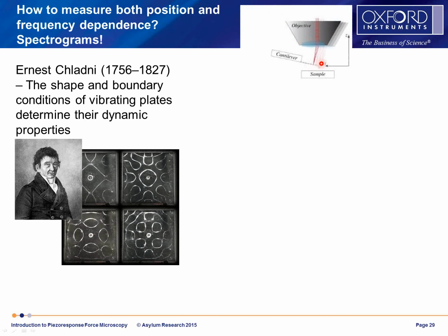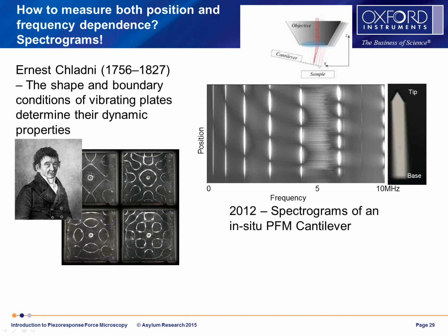We scan those photons using the optical detector and the AFM along the length of that cantilever. At the same time, we vary the frequency. We just sweep the frequency from, say, 0 to some high frequency. In the case I'm about to show you, 10 megahertz. And you generate these kind of pretty-looking maps of frequency and amplitude as a function of position from the base of the cantilever here up to the tip here. And you can see here's the first mode at about 300 or 400 kilohertz. Second mode, third mode, fourth mode, and so on, all the way up to a mode at 10 megahertz with all sorts of structure in it.